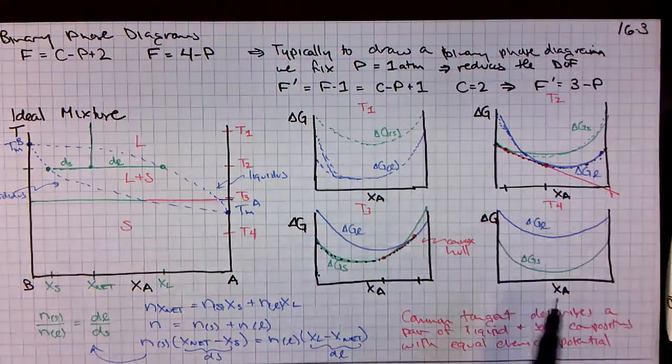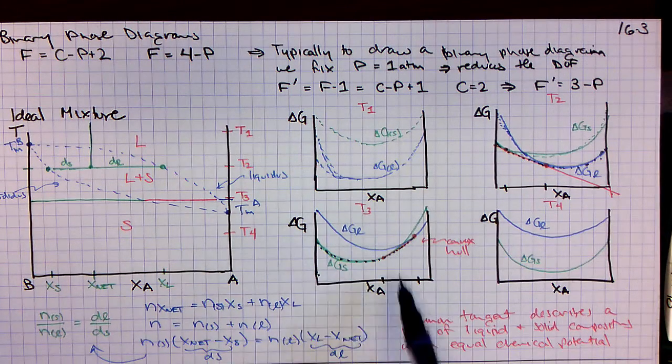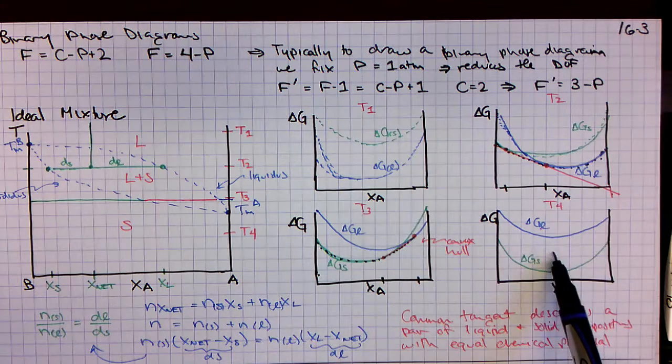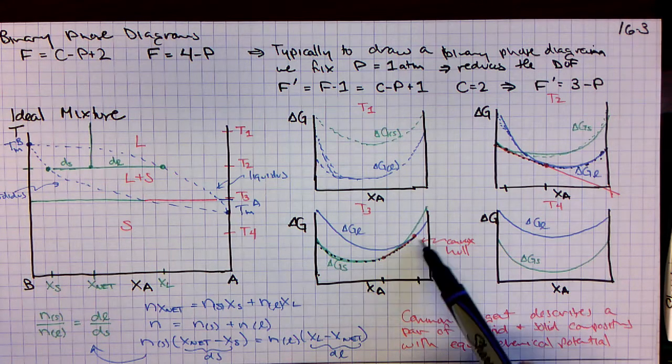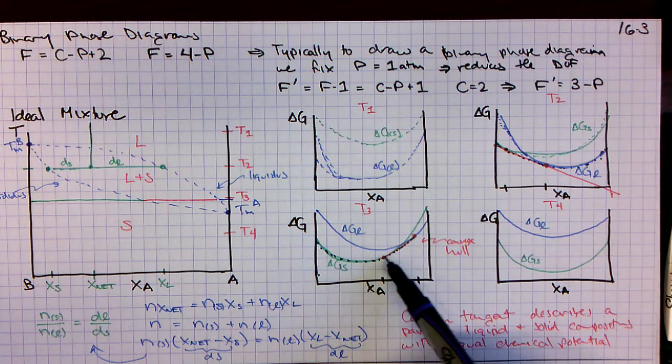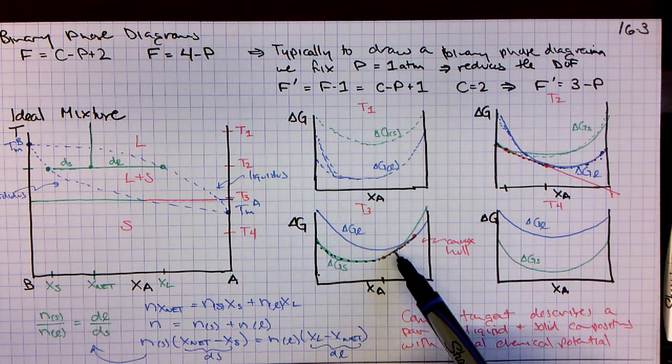So the important points here are, when you have free energy curves and you can plot them at different temperatures, it's important to look to see if they intersect, whether there are any points that are concave, and that the locus of free energies that describe the low energy of the system can't contain any concave segments.